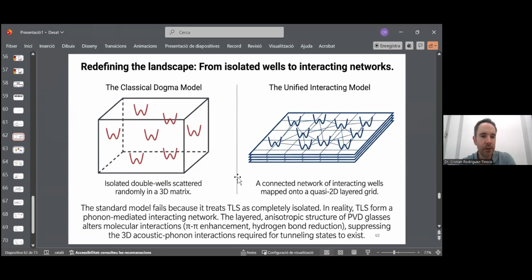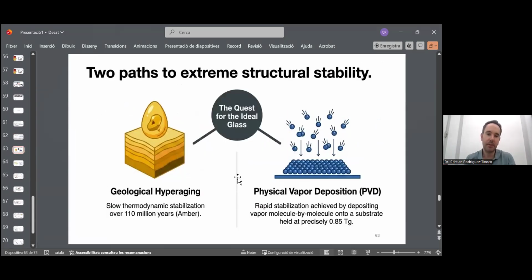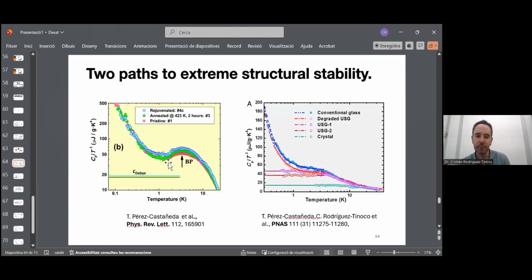Okay. Also, there was this comparison between this amber that Miguel Ángel also measured, the amber, the hyper-aged glass, a glass naturally aged for millions of years, with this PVD glass, this ultrastable glass prepared by physical vapor deposition that exhibits a similar thermodynamic stability, but by very different routes. So in the case of the amber, again, we still keep this TLS. Even being more stable, we still observe this TLS. That's why we concluded that the disappearance of the TLS was not due to the density, to the stability, but to the anisotropy.